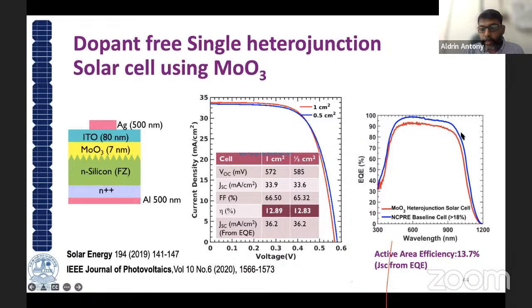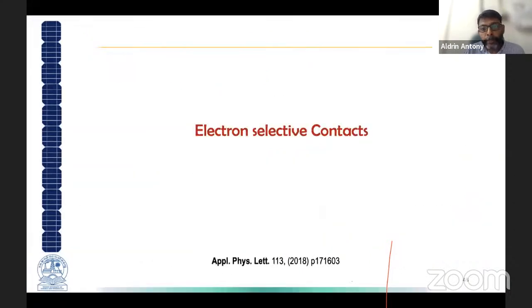And this is an EQE, external quantum efficiency, curve. You can see that even in the shorter wavelength region, it has very wide transparency, and it is much better than normal crystalline silicon solar cells with thermally diffused N layers on this side. But a lot of improvement is needed, because the passivation quality may not be as efficient as that of N-type crystalline silicon and normal homojunction solar cells. But it's a very low cost method, with which we could get an efficiency of 13% just by thermal evaporation of MoO3.